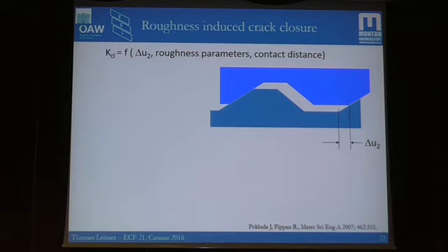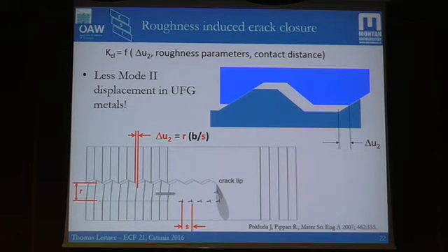However, it's not only necessary to have a certain roughness, but we also need displacement in the mode 2 direction, because if we wouldn't have this mode 2 displacement, the sides of the crack would fit perfectly into each other, and we wouldn't get crack closure. It was shown by simulation works that this displacement is reduced in ultrafine grained metals, because on the one hand we have a smaller size of the plastic zone, and on the other hand, we also have a more symmetric dislocation movement during deformation. So it's not just the size of the roughness and asperities, but also this reduced mode 2 displacement that leads to a reduced roughness-induced crack closure part in fine grains.